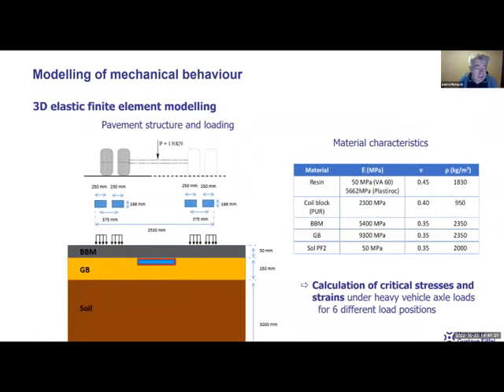So we did also some mechanical modeling of the mechanical behavior under wheel loads. And for that, we did in the first approach 3D elastic finite element calculations. So we simulated again the pavement with the embedded coil block. And we simulated loading by a standard French heavy vehicle axle, which is a 130 kilonewton axle with dual wheels. So we simulated the properties of the different materials, and we calculated the stress and strain fields under the heavy vehicle axle loads for different positions of the axle, positions where the coils are in the center between the wheels, and also positions where the wheels are on top of the coils or on the corner of the coils, to see the different effects when the loading is on the coils and when the loading is on the side.